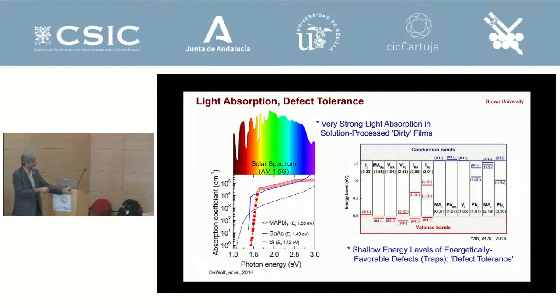So you can make a quick and dirty solution-processed film, and you can get more absorption than gallium arsenide. And that was a puzzle in the beginning when people started working on this. I was involved in a lot of the early thinking. The reason is that the point defects that form in these crystal structures, that are energetically favorable, are very shallow. They're either close to the valence band or the conduction band. Deep defects are not energetically favorable.